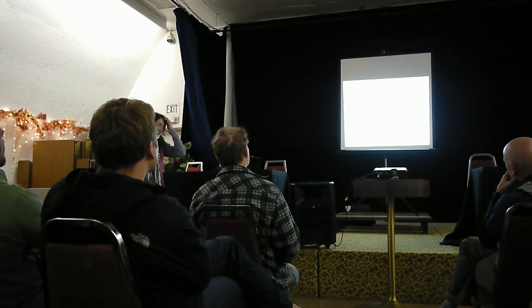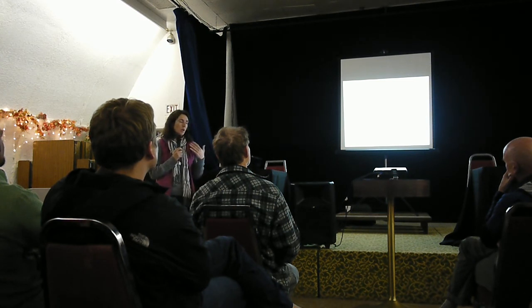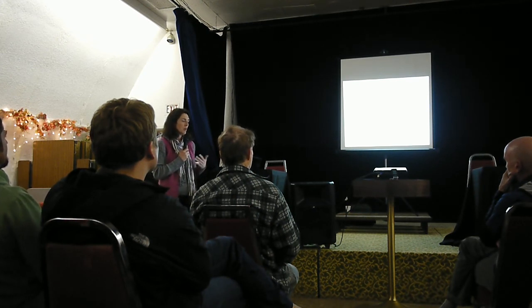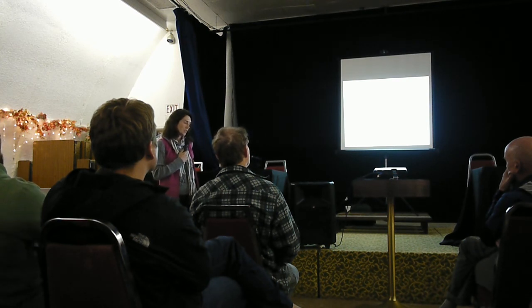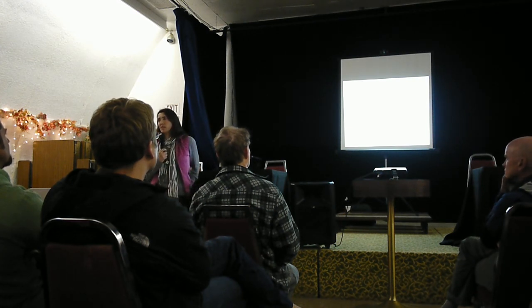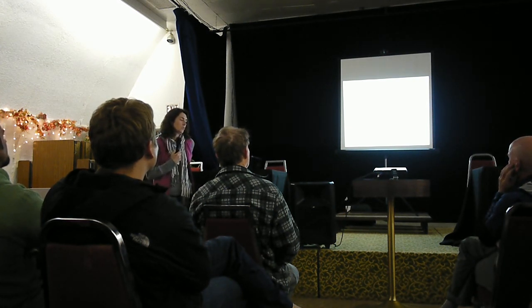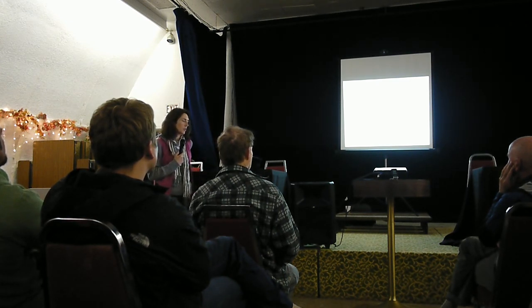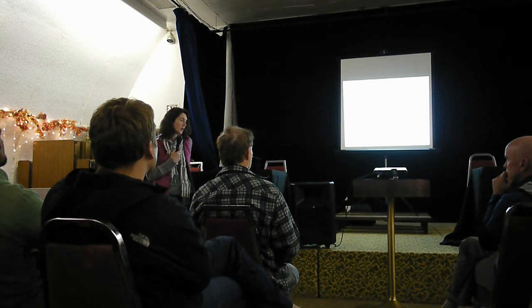So I want to talk just real briefly about the titanium replacement anchor. There's a couple of different grades. Mostly when people are talking about titanium, they're talking about grade 2, which is considered an unalloyed titanium. This is a great material. It's absolutely fantastic. It's immune to chloride attack at any stress level. There is no threshold stress above which this material undergoes SCC. Personally, I boiled the stuff for 28 days in the magnesium chloride, and I never saw any cracking, including the weld area.